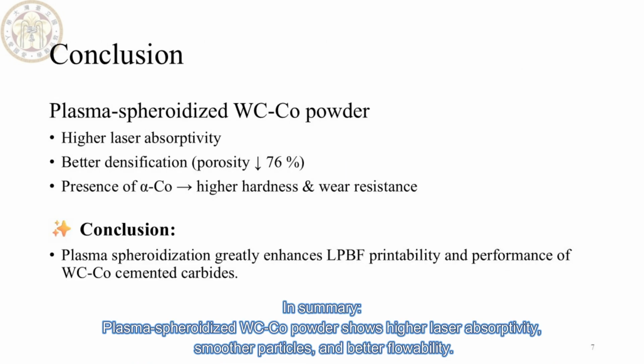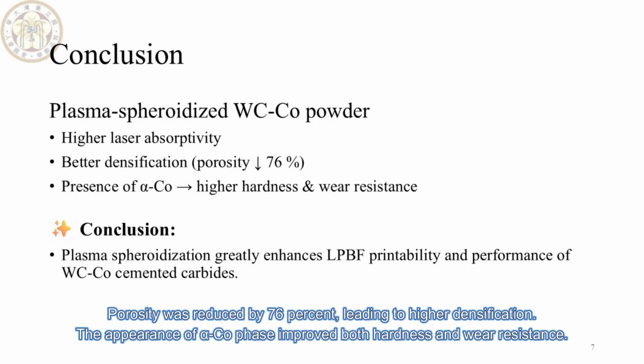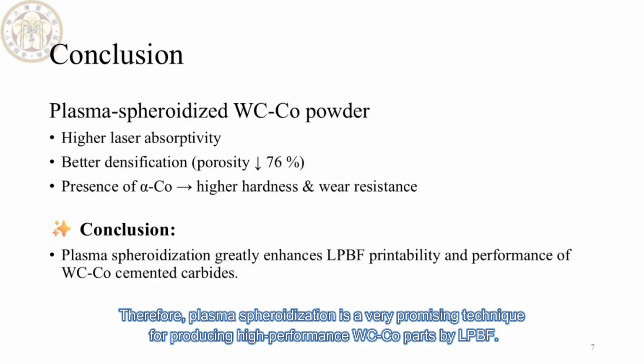In summary, plasma spheroidized WC-Co powder shows higher laser absorptivity, smoother particles, and better flowability. Porosity was reduced by 76%, leading to higher densification. The appearance of alpha-Co phase improved both hardness and wear resistance. Therefore, plasma spheroidization is a very promising technique for producing high-performance WC-Co parts by LPBF.